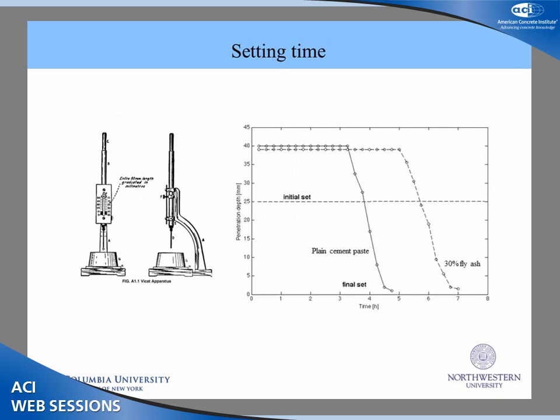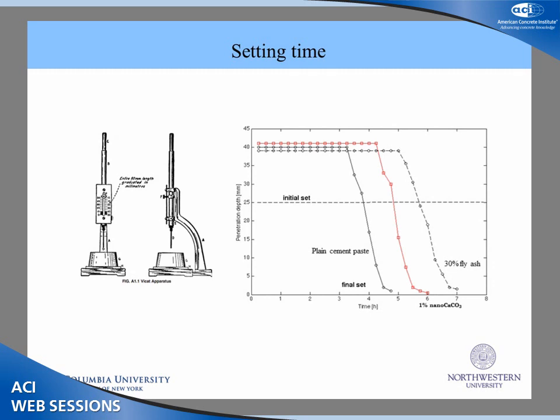First, we looked at setting time, which was measured using the Vicat needle test. So this is plain cement paste, and this is with a 30% fly ash replacement. As expected, there is a delay in setting time in both initial and final set. This is with the addition of 1% calcium carbonate nanoparticles. And this was treated with the PC superplasticizer, but wasn't subjected to sonication. But we see that the surfactants do have an effect, and it does shift the setting time up a little bit. Now with sonication, there's a more enhanced effect. So we see two things here. The surfactant is having an effect on dispersion, which helps to enhance its properties. But in addition to that, sonication is also aiding in the dispersion process.